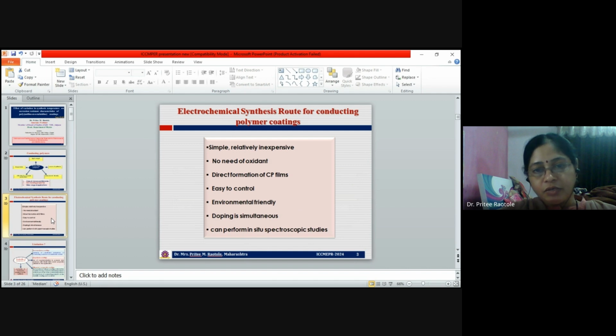We have used the electrochemical synthesis route for the synthesis of these conducting polymers because it is simple, relatively inexpensive, with no need of oxidant, direct formation of conducting polymer films, easy to control, environmentally friendly, doping is simultaneous and can perform in situ spectroscopic studies. Also, the quality of film is good by this method.